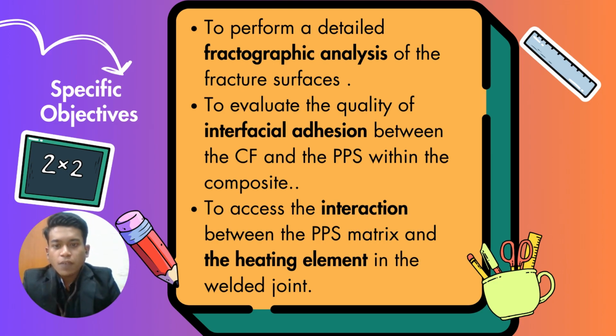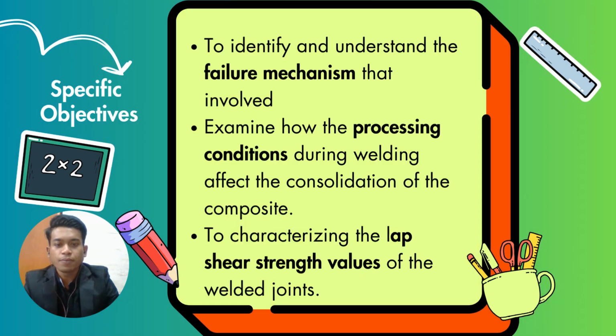The specific objective of the experiment is to perform a detailed fractographic analysis of the fracture surface to evaluate the quality of interfacial adhesion between the carbon fiber and the polyphenylene sulfide within the composite, to assess the interaction between the polyphenylene sulfide matrix and the heating element in the weld joint.